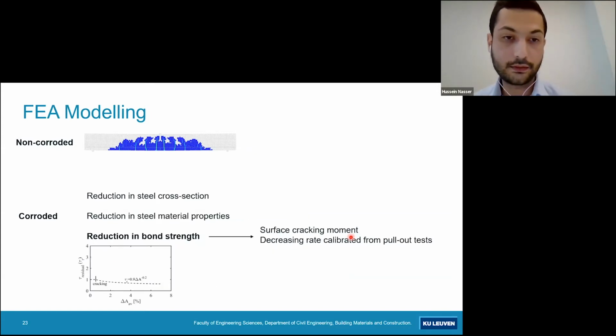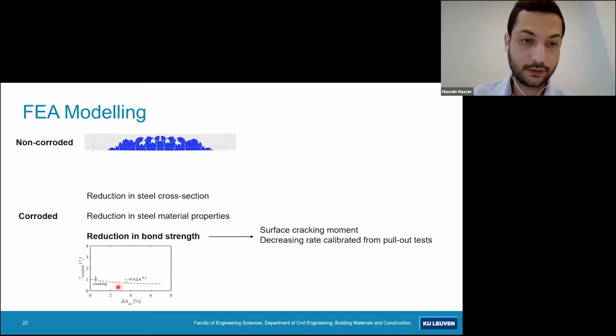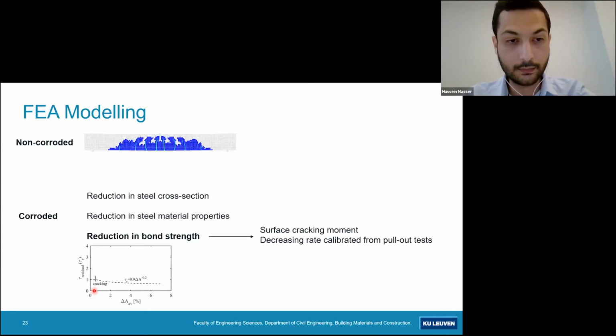Finally, I also took into account the bond deterioration. I assume in this figure here that when the concrete is not cracked, then the bond is not affected by the corrosion, whereas the moment surface corrosion cracking occurs, then a decrease in the bond strength has been calibrated according to pull-out tests. The decreasing rate, -0.2, was obtained based on pull-out tests that have been done in the framework of the same project.